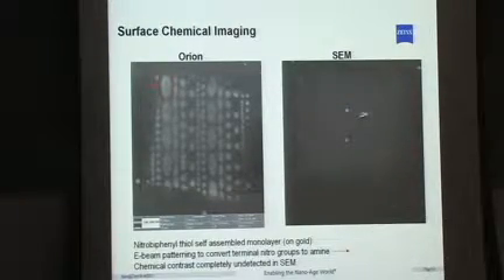This is an example showing how we have terrific surface sensitivity. This is a single self-assembled monolayer on gold. This monolayer was built up here and then patterned. They removed some of the atoms at the very end of it, and we were able to see that contrast difference of where it was patterned or where it wasn't. A very subtle difference in the top atomic layers. In an electron microscope, because you get that deeper penetration, you don't always get that surface contrast.